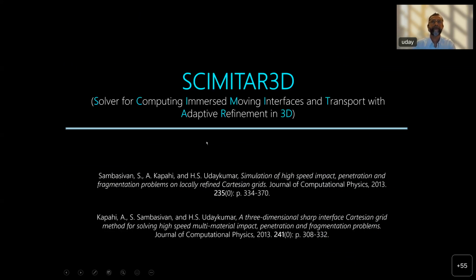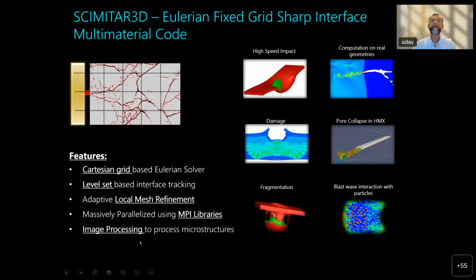So just to describe very briefly in a couple of slides what Scimitar 3D is. Scimitar 3D stands for solver for computing immersed moving interfaces and transport with adaptive refinement in 3D. And these were publications that our group put out over the last decade or so, various kinds of problems solved with Scimitar 3D. Just to show a variety of things that we have done. So we've done problems of high-speed impact, computation on real geometries, microstructures, and so on. Damage mechanics, pore collapse, of course, three-dimensional and two-dimensional pore collapse in HMX and other materials. Fragmentation, impact and fragmentation, and blast wave interaction with particles. So compressible multi-material, multi-phase flows is what Scimitar 3D is capable of doing.